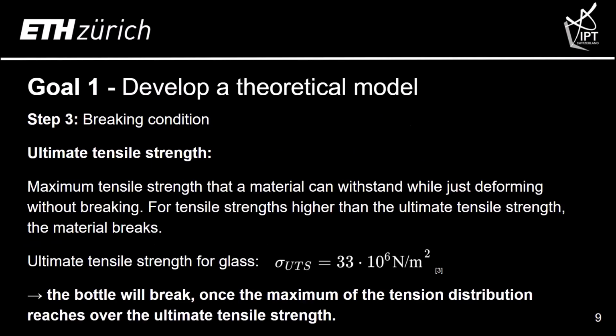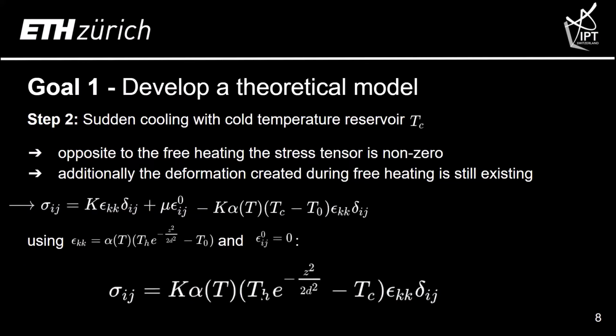And now I wanted to find a condition that justifies if my bottle breaks or not. And for that, I turned to the concept of the ultimate tensile strength, which basically is a measure for how much force per area I can apply on a bottle until it breaks at a certain point. For glass, this value is given by 33 megapascal. And that is basically my condition for whether my bottle breaks or not. And as you could see from the model here, the point where it should break is at the maximum of the temperature distribution, because there it will be the first place to reach this critical tensile strength.